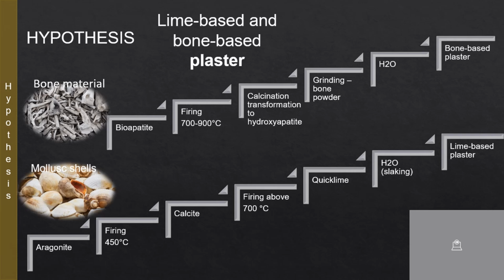Bones are composed of bioapatite and transform into hydroxyapatite by firing above 700 degrees. Mollusk shells are composed of aragonite and decompose into calcite by firing above 450 degrees. Heating calcite further to 700 or 800 degrees removes CO2, forming quicklime, which, when slaked with water, produces hydrated lime. This material hardens through carbonation, forming a durable lime plaster. Our experiment tested whether this process could produce plastic yet durable inlay material suitable for pottery decoration.